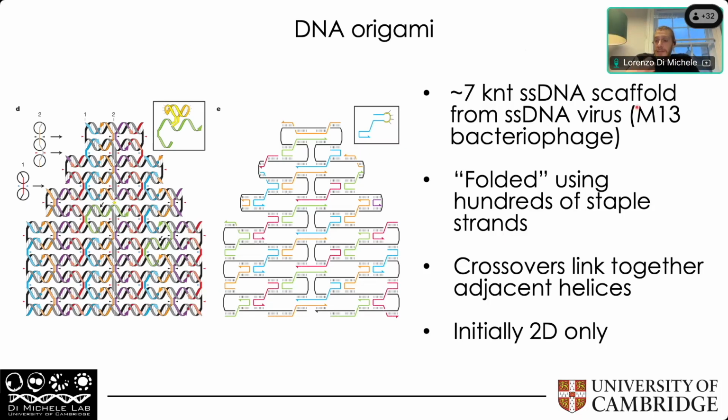This is not a synthetic DNA. This is a DNA that comes from biology. It's the single-stranded DNA genome of a bacteriophage, which is a virus that infects bacteria, called the M13 bacteriophage. And that's about 7,000 nucleotides in length. The idea of DNA origami is that you take this long scaffold and then you fold it in a certain shape using your shorter synthetic DNA molecules.